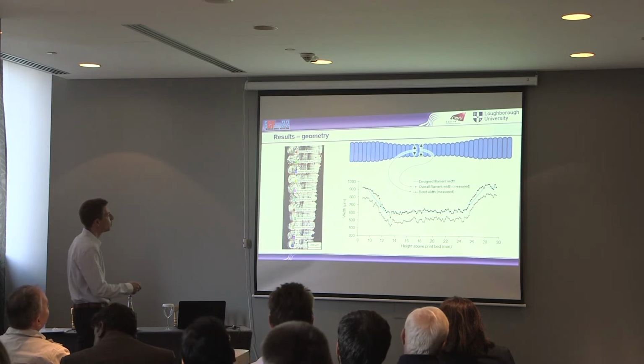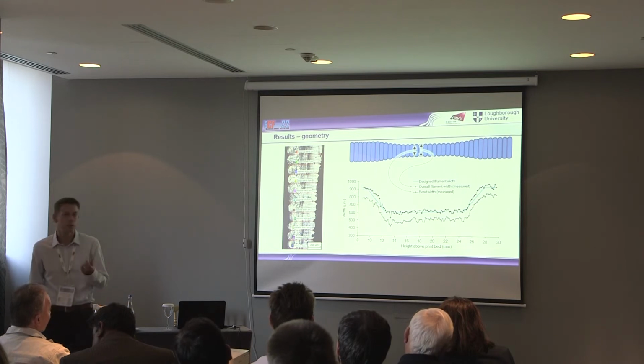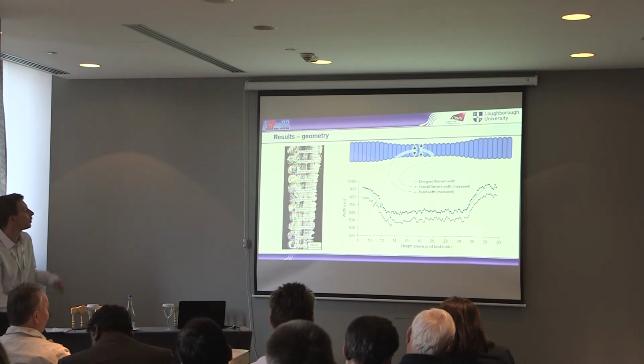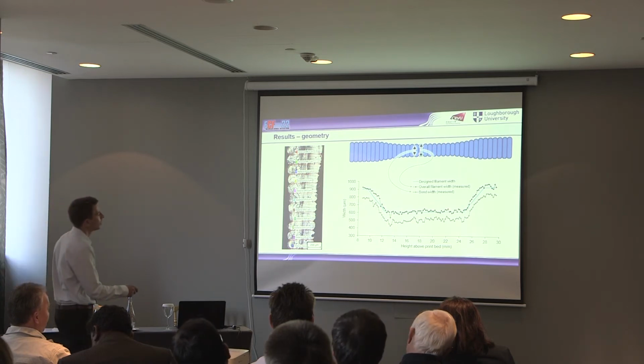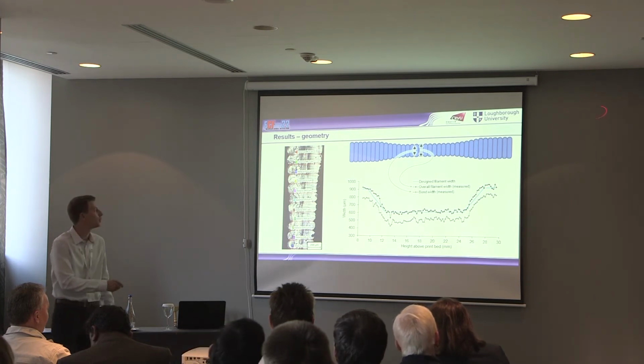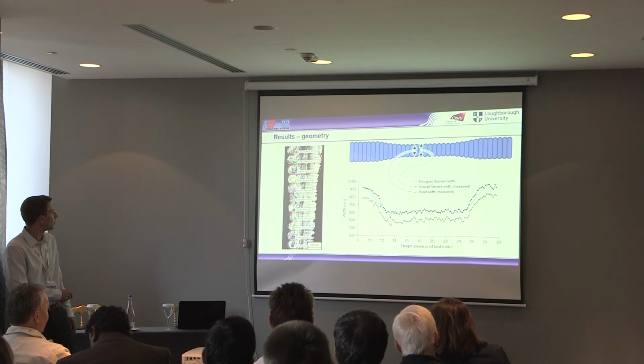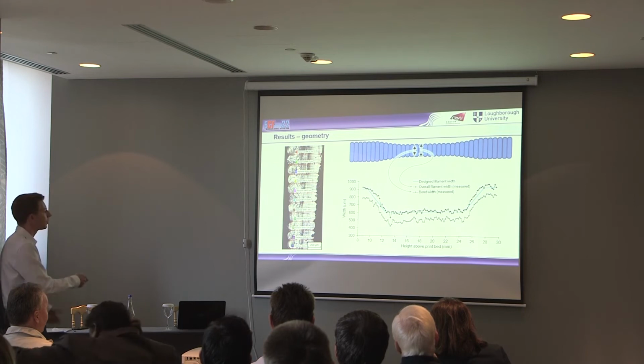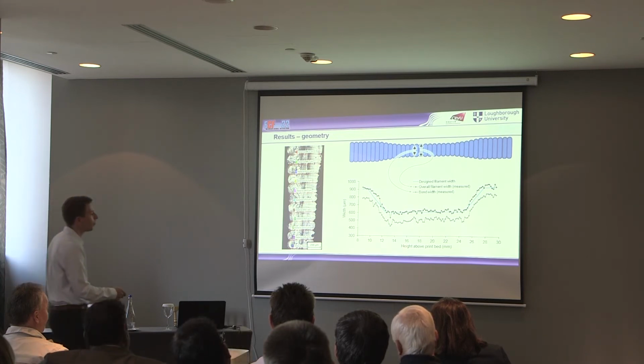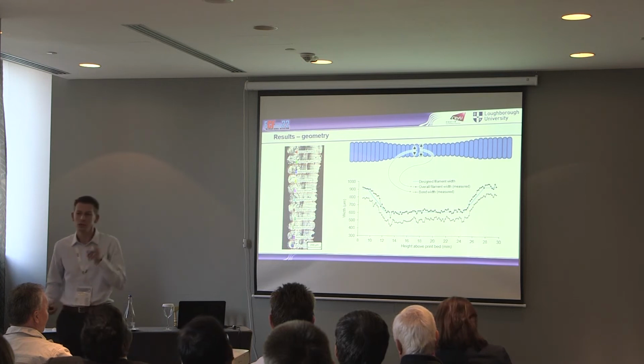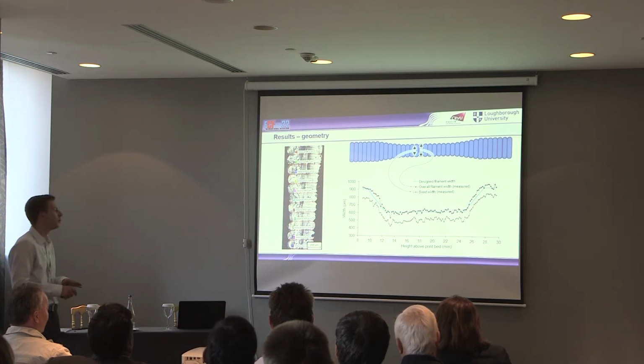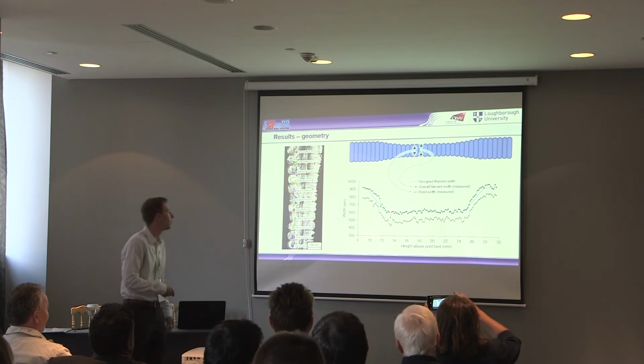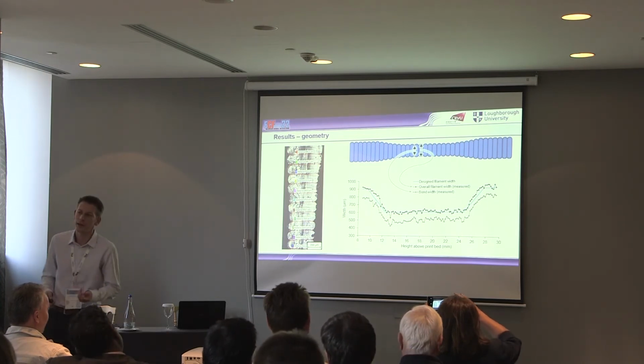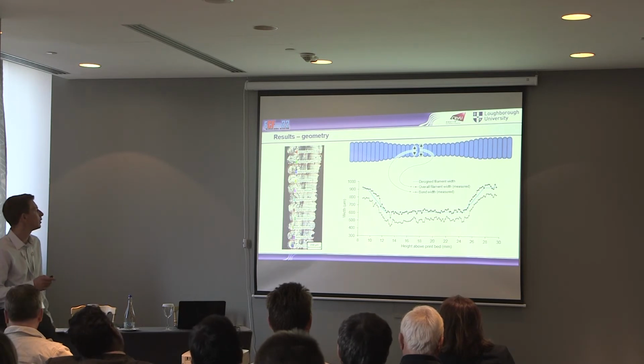The blue line here is showing the width, 900 microns in the grip sections, coming down to 600 microns in the narrow gauge section, and this is the overall width of the filament. Each point is one filament, so there are a lot more filaments than in this picture. And then we also have this bond, so you can see the bond is slightly narrower than the overall width of the filament, so we've measured the bond as well to check. And interestingly, I think this is probably where it will fail, because it's got the smallest bond, and you only need to fail one point, one single layer is all that will be failing. So it's pretty regular, so we're not getting some really awful layers with too small ones.